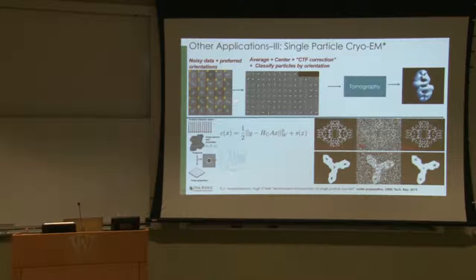tomography. So what we're looking at in this application is, can we go directly from here to the reconstruction? Can we go from raw measurements by modeling the process of formation? And here we have demonstrated using some simulated data that we can. And the forward propagator not only includes random orientations, but also something called the contrast transfer function. So it's the propagation of the wave, where you have an incident beam on a particle, then you have a propagator, which creates the data. That's the model.